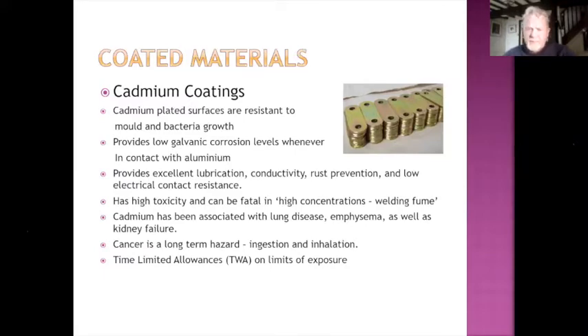Cadmium has been associated with lung diseases such as emphysema, as well as kidney failure. Cadmium was at one time a constituent of many soft solders. That has been taken out because of the very nature of this material. It's been a long-term hazard in terms of ingestion and inhalation, and there is a time-weighted allowance on the exposure to that material. So in that instance, I would advocate not only local extraction, but definitely an air-fed mask with that particular material.